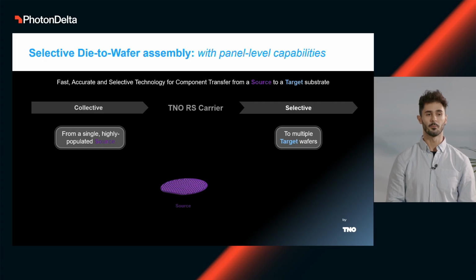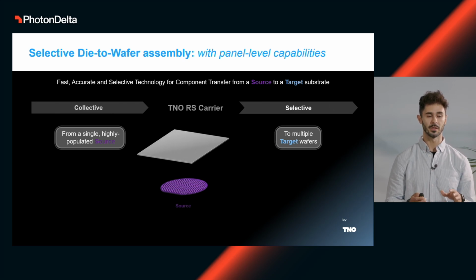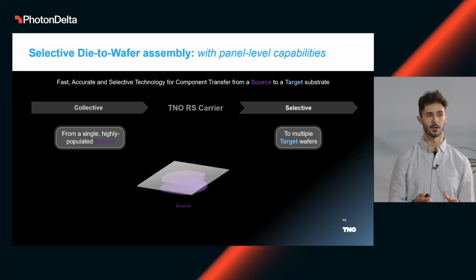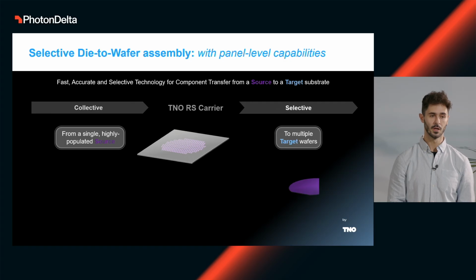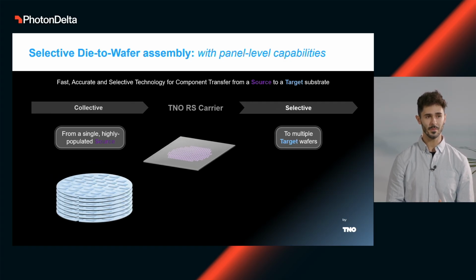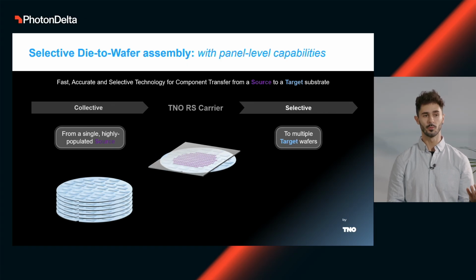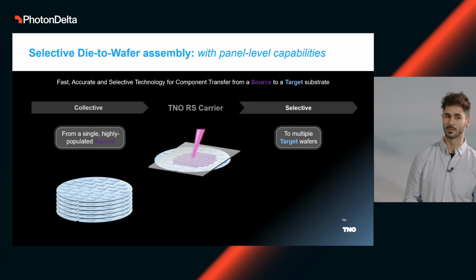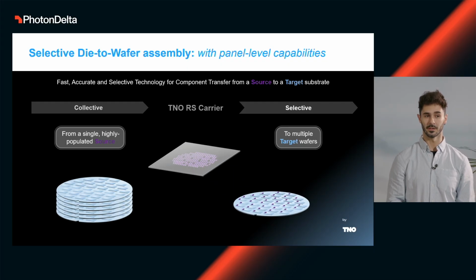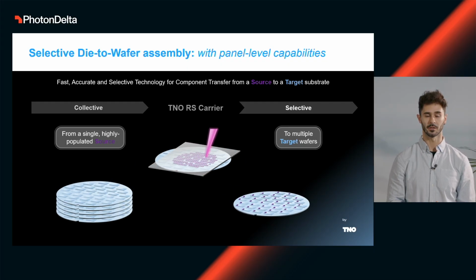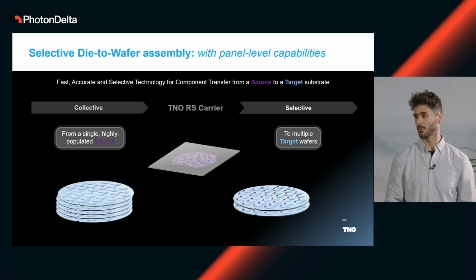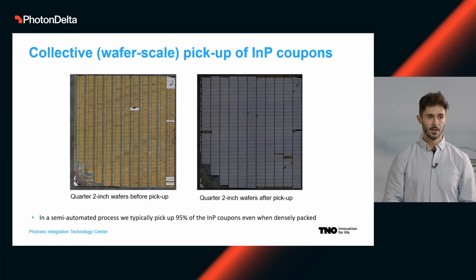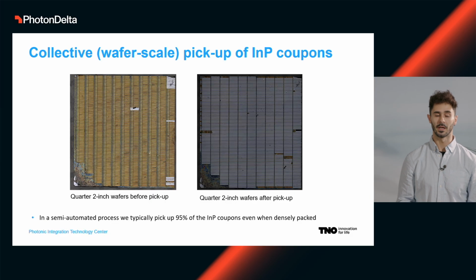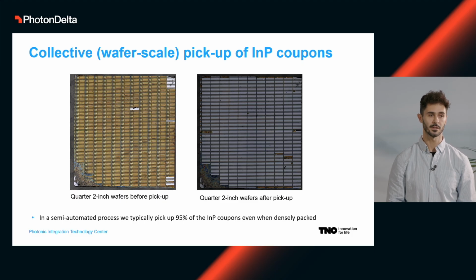A key part of this technology is that it is a combination of a collective process and a selective process. Initially, our proprietary carrier picks up all the components at once, which can be very densely populated and fabricated on the source wafer all together, and then from one single source wafer, you can populate many different receiver wafers. So the scalability of this technology is extremely relevant, and it can make a very big economic impact when you look at components per hour or wafers per hour that you can populate. This is an example of our collective wafer-scale pickup process with lasers.